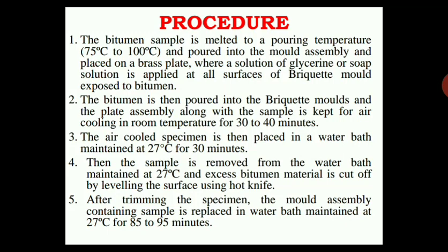The next part is that the bitumen is poured into the briquette molds, and the plate assembly along with the sample is kept for air cooling at room temperature for 30 to 40 minutes. After pouring the bitumen into the molds, we need to keep it for air cooling for 30 to 40 minutes.